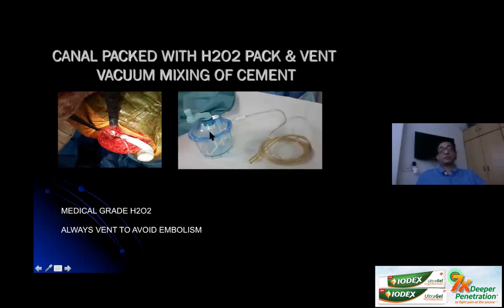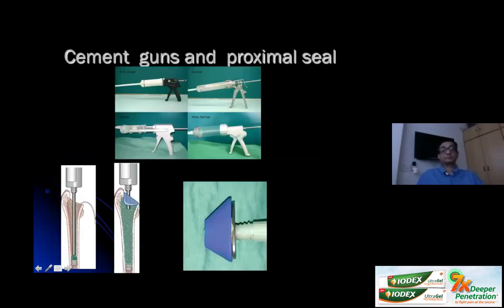Again, whenever possible, I try to use the vacuum mixing system, which is available easily with most of the manufacturers now, so that there are no pores or voids or air bubbles trapped in the cement mantle. You get a nice uniform cement mantle. Then use the cement gun with a proximal femoral seal and your vent, so as to start retrograde filling of the cement. Fill the cement till the tip.